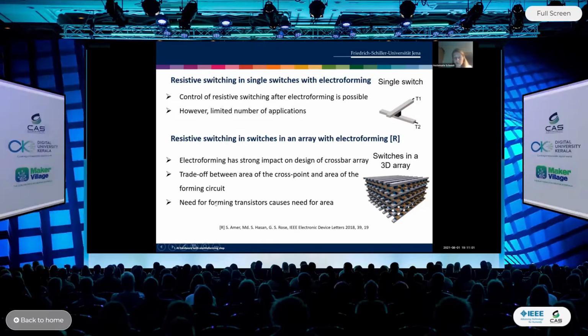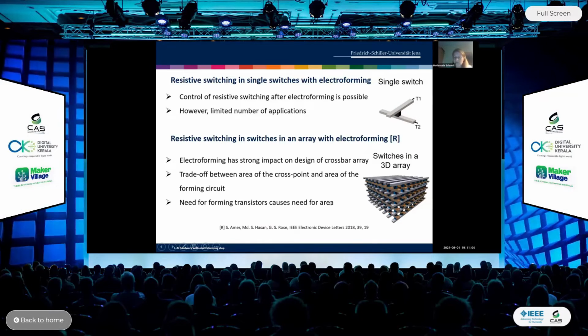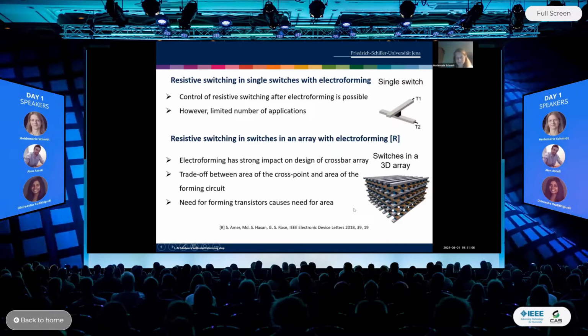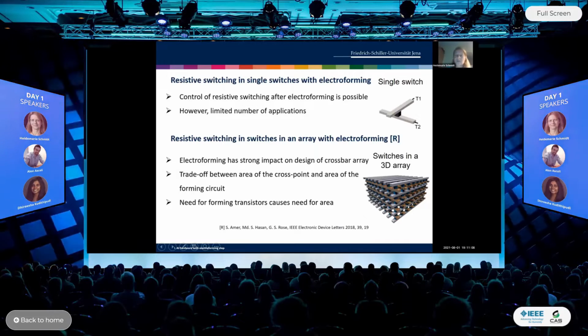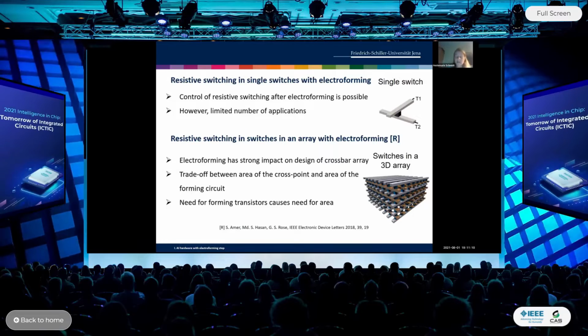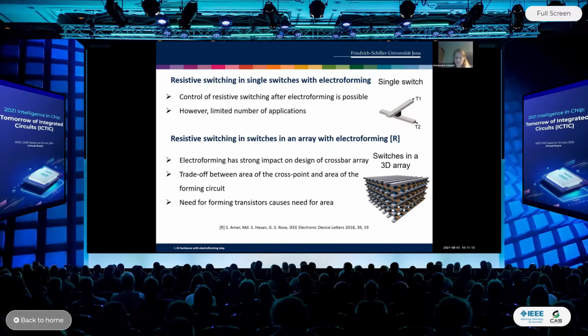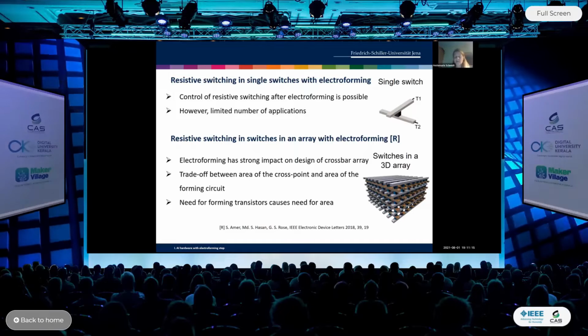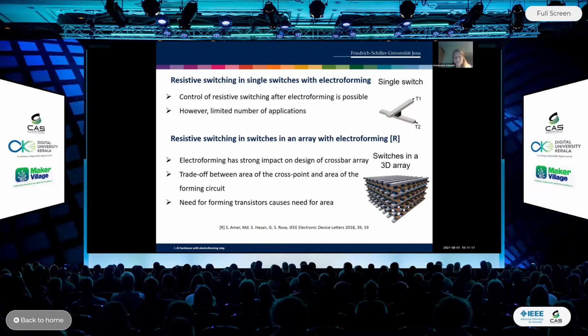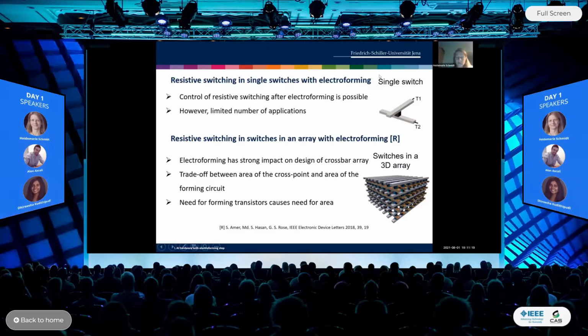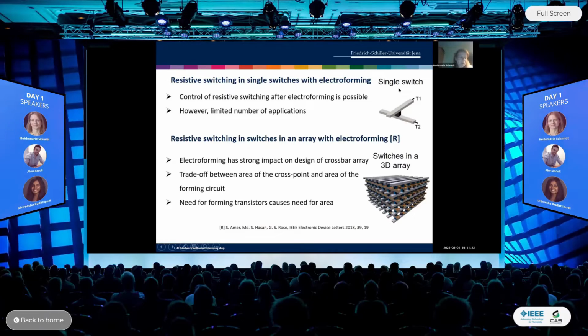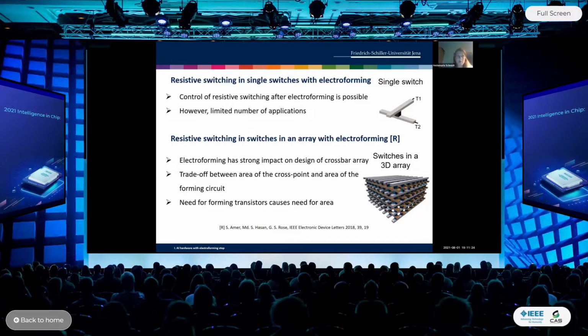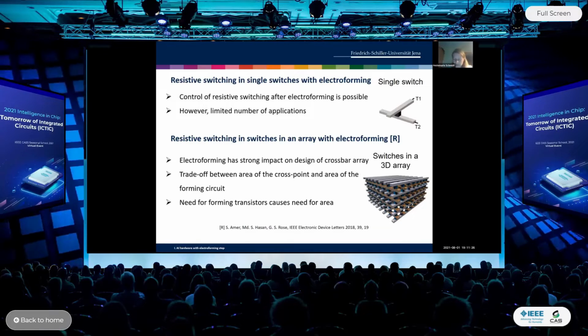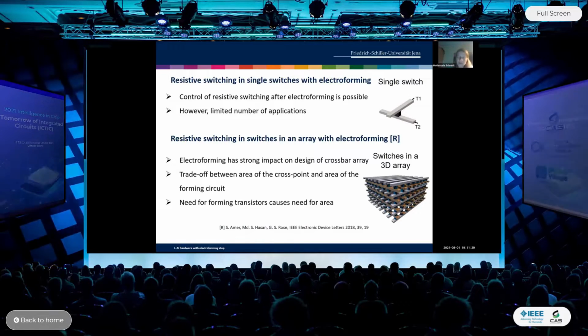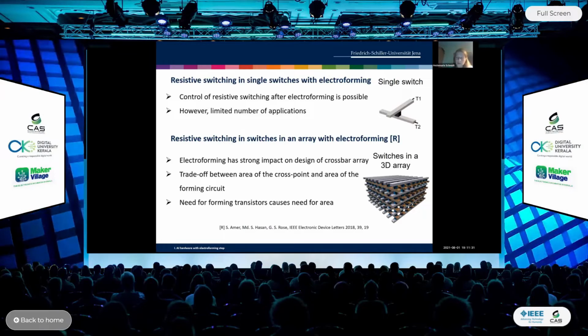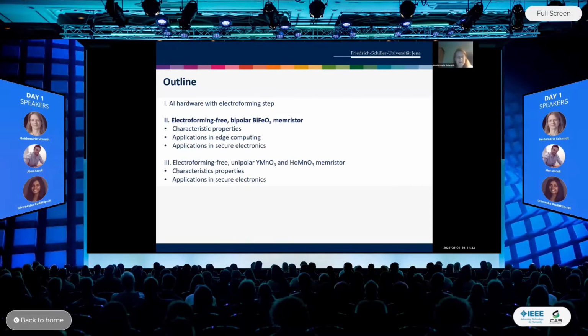And for sure, the forming transistors also need additional area. So there are several disadvantages if you think about upscaling and increasing the number of memristors, if those memristors need an electroforming step. And this was the motivation for our work. We wanted to look whether there exist other materials where the resistive switching has a different physical mechanism underlying it, and where no electroforming step is needed.